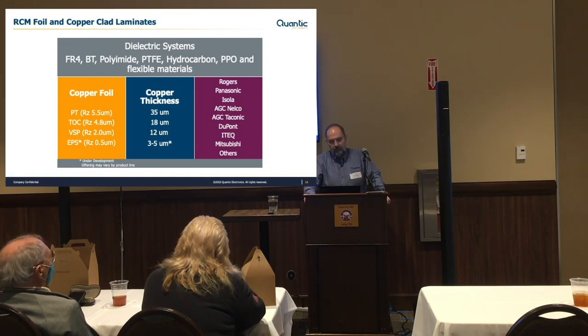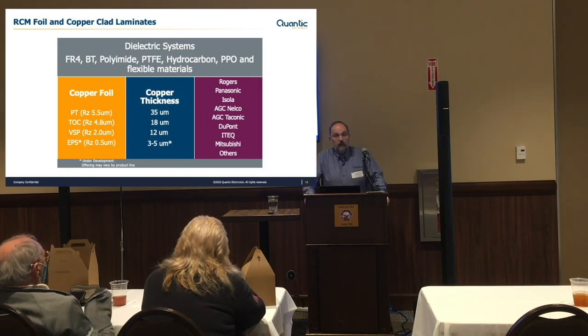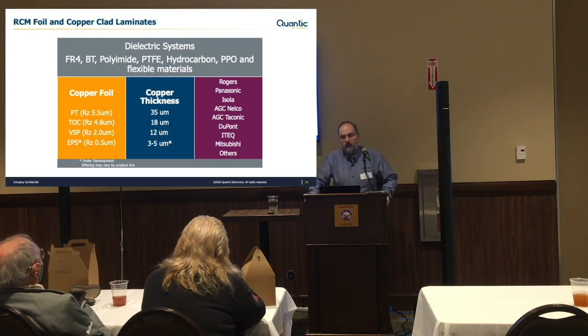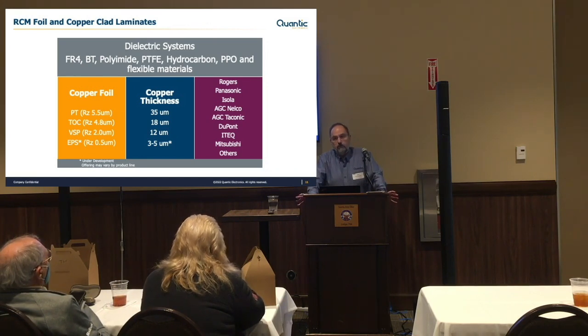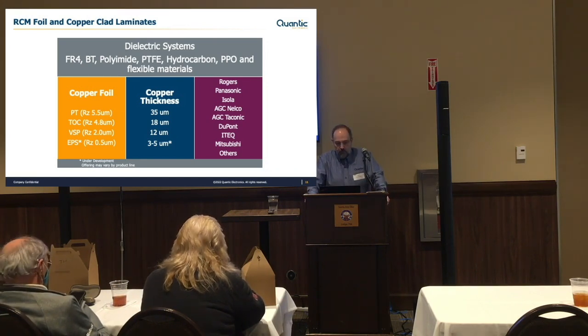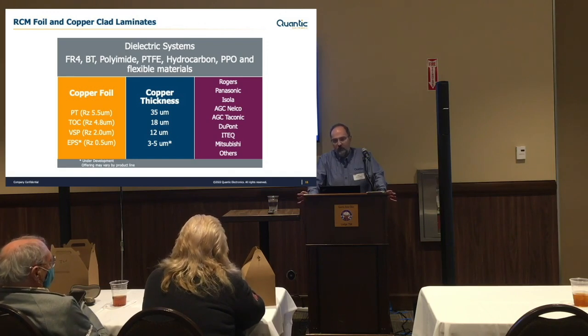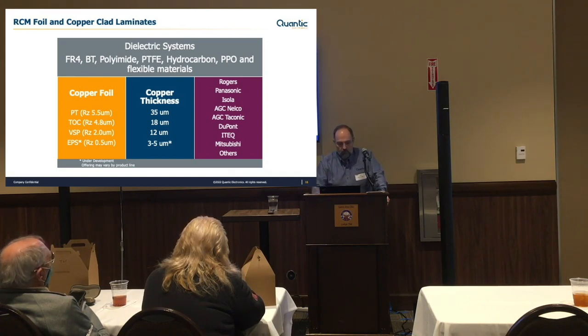And we've basically been tested on all the different resin systems out there. So we work with Rogers, Panasonic, Isola, the AGC companies, both Nelco and Taconic, DuPont, so it can be put on flex material. A number of times it's put on the flex, and because these layers are so thin, they have very good flexural resistance. So you can make flex resistors or flex heaters using this material, as well as ITEQ, Mitsubishi, and others. So there really aren't too many laminate materials we haven't been on. So it works very well with all of them.